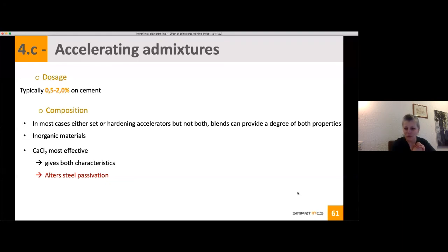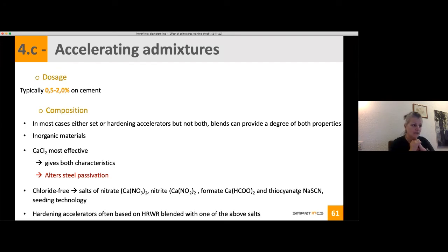Calcium chloride, maybe you have heard, is really one of the best accelerators. It gives both characteristics, set and hardening acceleration, but a big negative effect is that it alters the steel passivation due to the chloride it has. So this is an accelerating admixture that you should not use where you have reinforcements. Then you have chloride-free accelerators. These can be salts of nitrate, nitrite, or other salts.